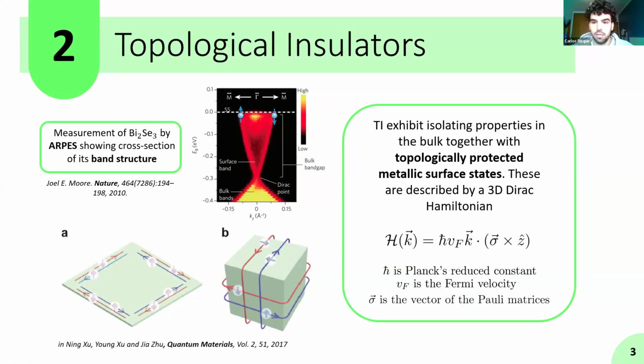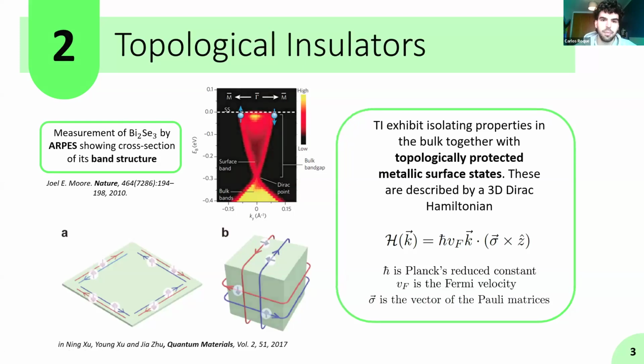These states are described by the three-dimensional Dirac Hamiltonian, and from this Hamiltonian it is theoretically predicted that at high symmetry points of the Brillouin zone, the band gap should close in a structure called the Dirac cone, and this was also experimentally observed by ARPES measurements. Here you have an example with bismuth selenide, which is a well-known topological insulator material.